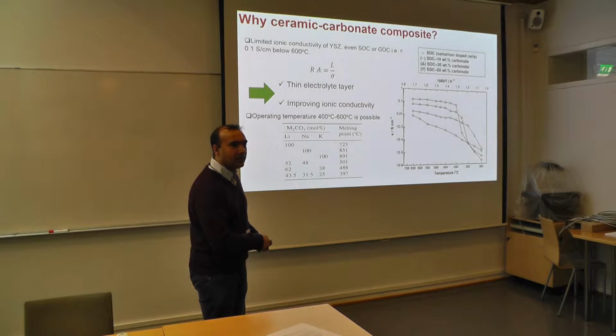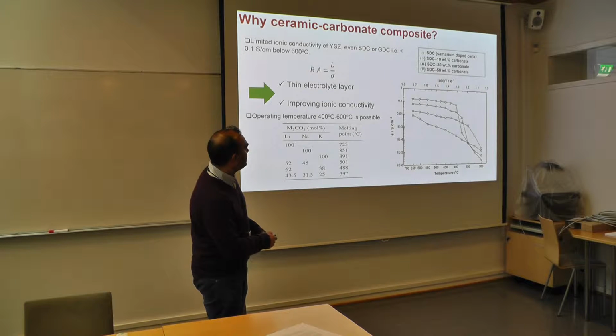So generally, we see in case of solid oxide fuel materials, there's a straight line in the Arrhenius plot. But here we see some kind of a jump, for example, in this case, over 400, there is a jump here. And we notice here that when we increase this carbonate content, for example, in this case, we have pure SDC, samarium-doped ceria, which is like this here. But when we add 10% of carbonates, so it's 90% of solid oxide ionic conductor and 10% carbonates, ionic conductivity improves in this temperature range. When we increase carbonate content, it increases even more. And then this is in case of 50%. So in this case, we have 50% carbonates, 50% samarium-doped ceria, and we improve its ionic conductivity.